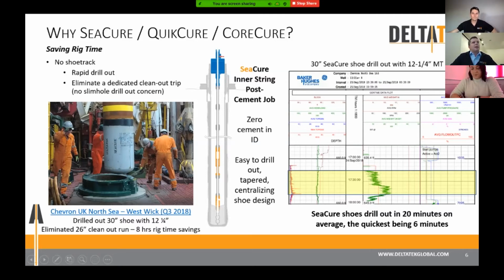But in addition, when you look at just comparing the time taken to drill out a conventional poured shoe track of 100 to 150 foot axial length versus SeaCure, giving you just a neat little 3-foot shoe to drill out with an easy to drill out tapered centralized shoe design, our shoes drill out in typically 20 minutes, the quickest being 6 minutes, versus what our customers routinely report is a 4 to 6 hour typical drill out time for a poured shoe track.